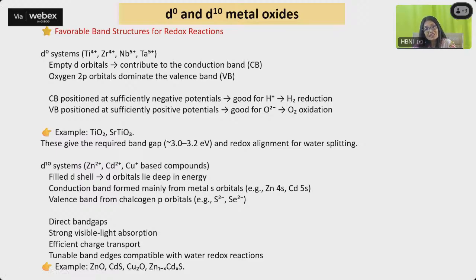What happens when you're using a d10 system? These have filled d shells, so these d orbitals lie very deep in energy. The conduction band is formed mainly from the metal s orbitals like the zinc 4s or the cadmium 5s. The valence band is from the chalcogen p orbitals like sulfide or selenide. So what you get is a direct band gap material which has very strong visible light absorption. There is very efficient charge transport, and there are tunable band edges which are compatible with the water redox reaction.